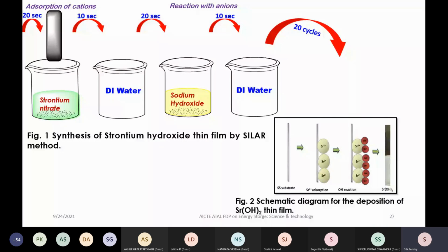strontium nitrate, and here DI water and DI water, and sodium hydroxide. Basically we started this work having no experimental facility. And it is very interesting to know that we are having these 4 beakers. With the help of these 4 beakers and the chemicals, and with the help of this substrate, we tried to see whether we are able to deposit this thin film or not. So in this process that we have done,